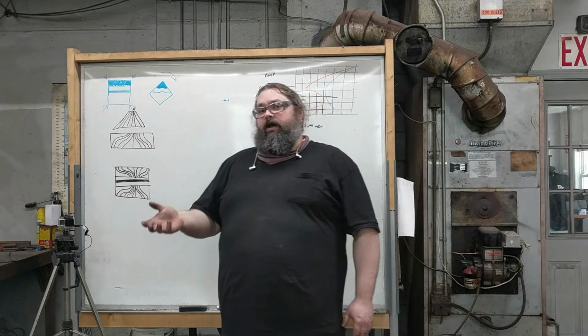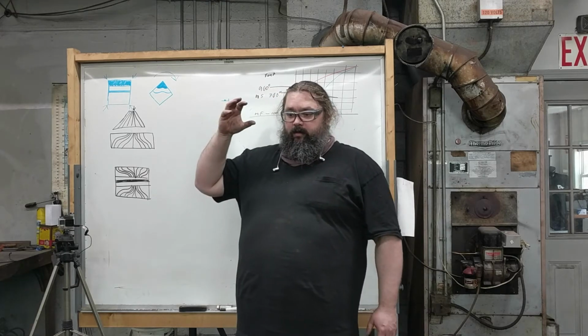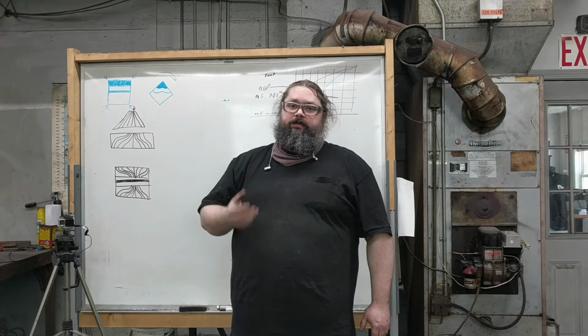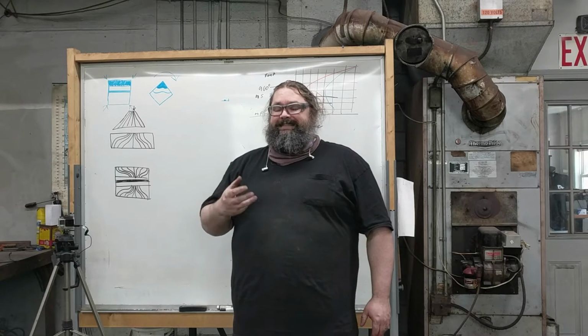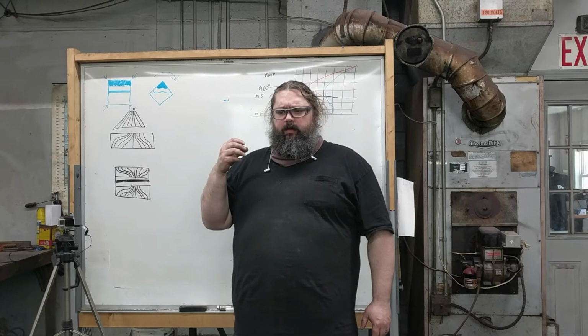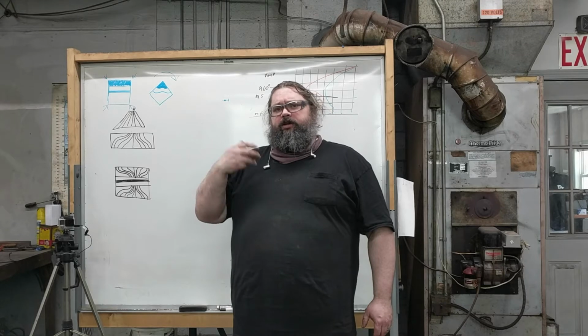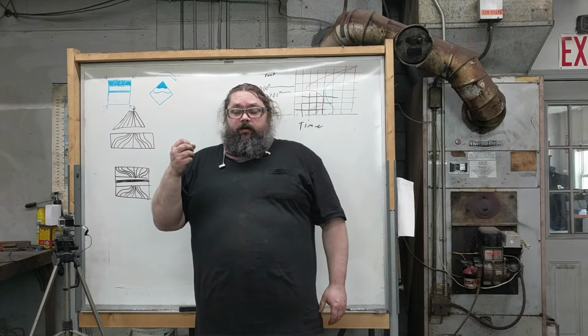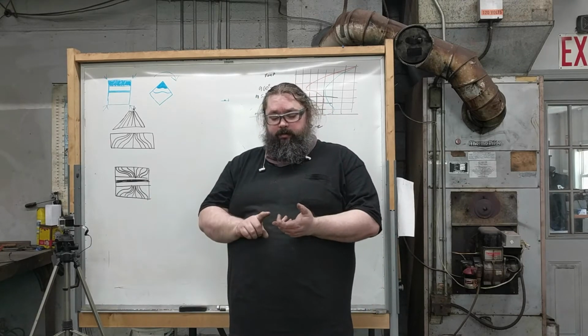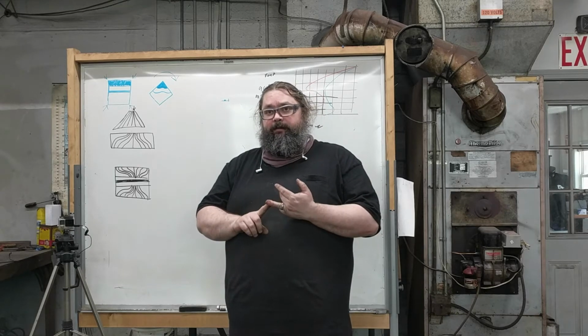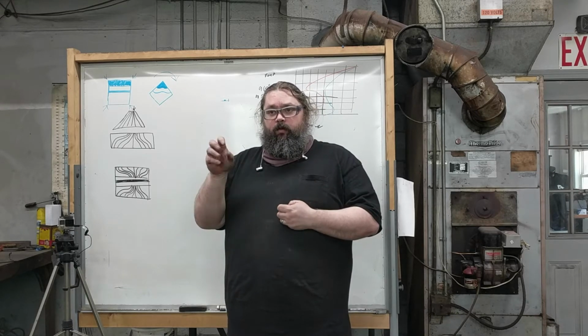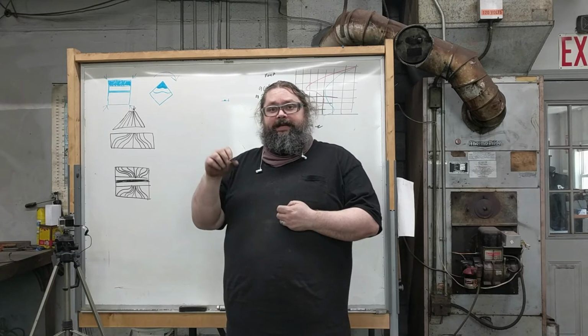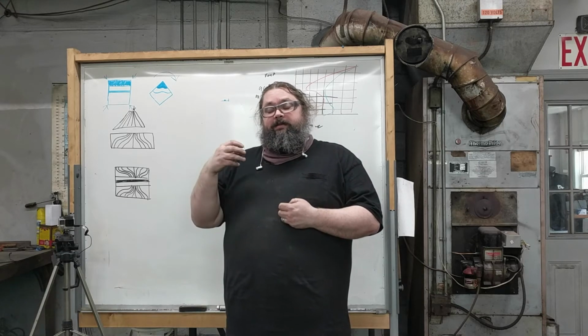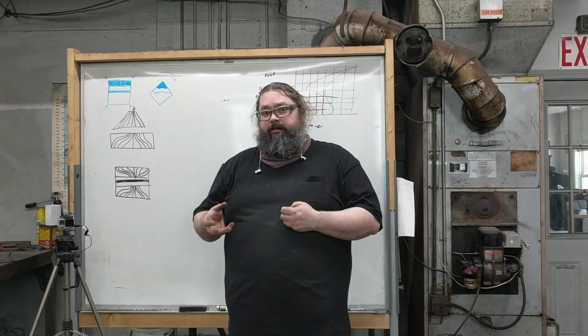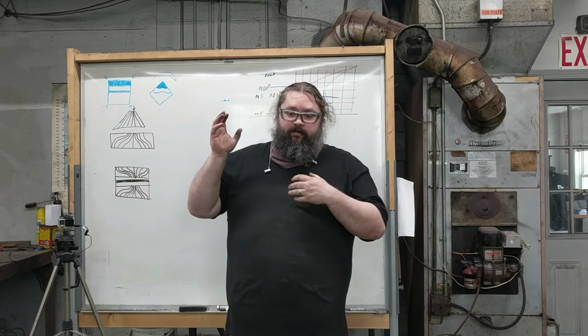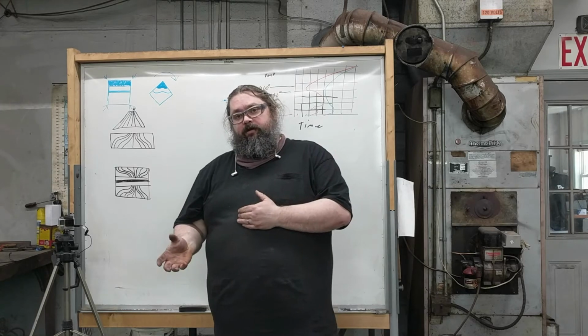If you do not use cryo, what ends up happening is you get a large amount of retained austenite. Austenite is not stable at room temperature, and what will happen with that austenite is it'll start to convert to martensite. It'll convert through dislocation, in other words, being bent or smacked or tapped. Any impact to the knife will convert little pockets of austenite to martensite. The problem is then it's martensite, but it's untempered martensite. So we need to find a way to force that conversion so that we can temper the martensite.